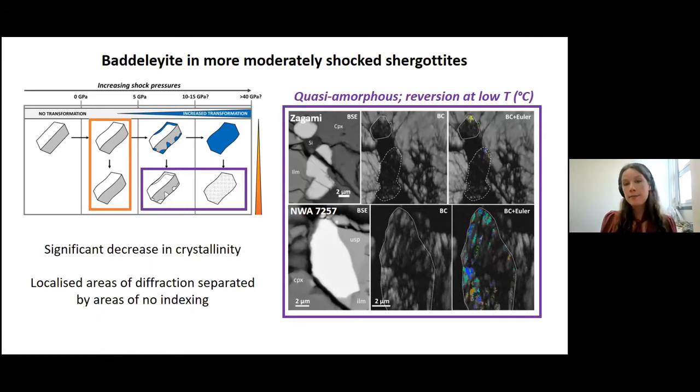And similarly reported microstructures were reported in 5298 in the Darling et al. paper. And actually TEM lift-outs of these do show nanostructural ordering. So I think we'll see these are truly quasi-amorphous structures. And we form these by partial to complete transformation of orthorhombic zirconia polymorphs, but rapidly reverting them at low post-shock temperatures. This inhibits significant nucleation of monoclinic zirconia and produces the quasi-amorphous structures we see.